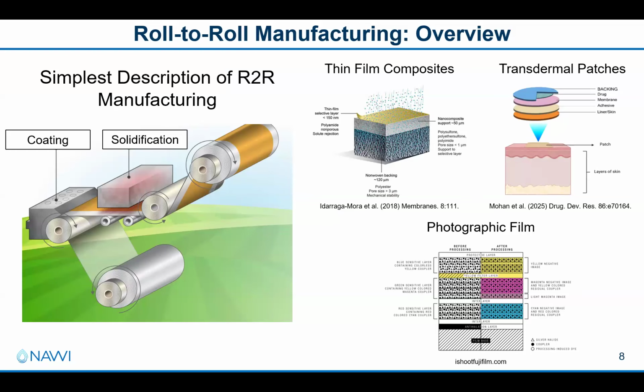So for a very, very simple description of roll-to-roll manufacturing, especially for, say, membranes, first you would have a substrate that is wound onto some roll that you pass through a system or a series of different rollers through a coating station, where at the coating station, a liquid precursor to whatever material you want to make is deposited onto the substrate. The substrate is then fed through a solidification station, where if the liquid precursor is a dissolved polymer solution, the polymer solution can be dried, removing the solvent to solidify it. Or if you say have a UV cured material, the material could be cured to achieve solidification.